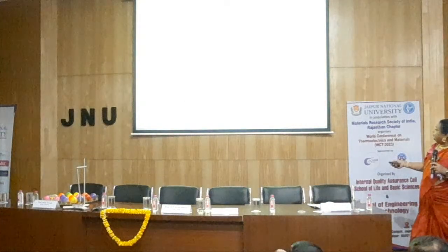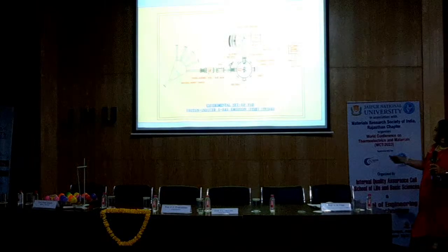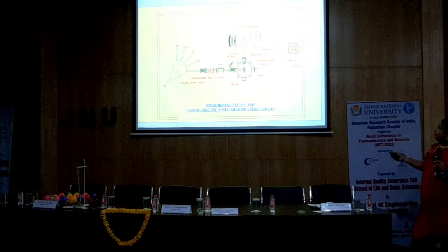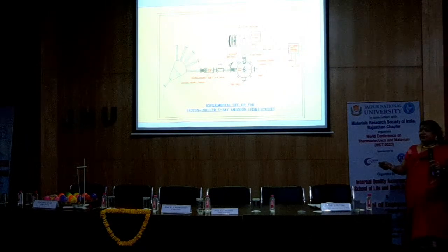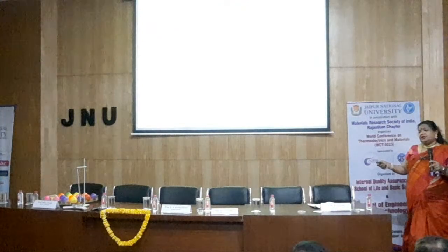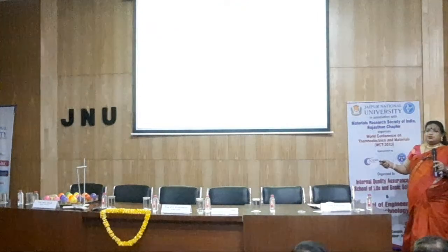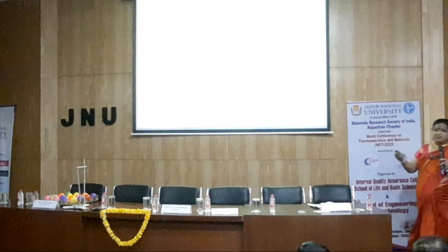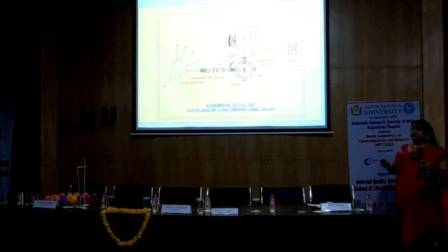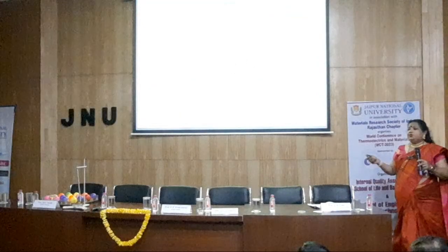Next. So here the electronics is almost the same. You see the setup. Everything is the same except it is in a chamber. I would have shown you the difference, but I can as well tell you that for photons you get 10 raised to 8 photons per second. In protons you get 10 raised to 12 protons per second. This is the flux. It's better. And for synchrotron, it's much better, 10 raised to 17. So depending on your problem, you can use your beam.